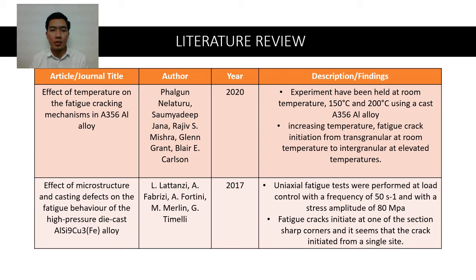As for the literature review, its purpose is to identify research articles before I proceed with my research. One of the articles that I read is Effect of Temperature on the Fatigue Cracking Mechanism in A356 Aluminium Alloy. This article was published in 2020. In this article, the experiment was held at room temperature, 150 degrees Celsius, and 200 degrees Celsius using a cast A356 aluminium alloy.